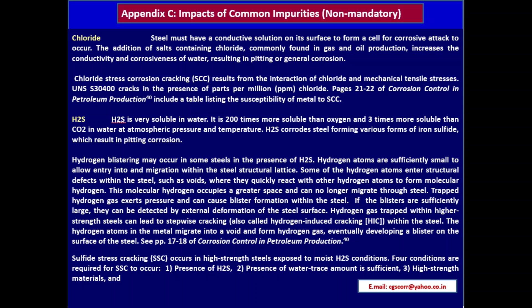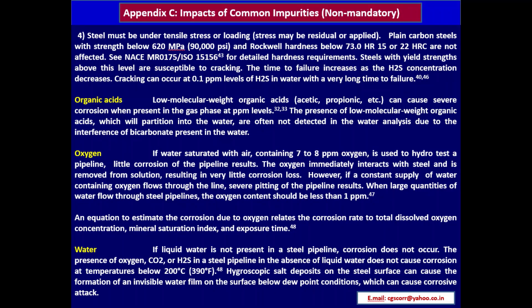Sulfide stress cracking (SSC) occurs in high-strength steels exposed to moist hydrogen sulfide conditions. Four conditions are required: (1) presence of hydrogen sulfide, (2) presence of water (trace amounts are sufficient), (3) high-strength material, and (4) steel under tensile stress or loading (stress may be residual or applied). Plain carbon steels with strength below 620 MPa (90,000 PSI) and Rockwell hardness below 73 HR15N or 22 HRC are not affected. Steels above this level are susceptible to cracking. Time to failure increases as H2S concentration decreases; cracking can occur at 0.1 ppm H2S in water with very long time to failure. See NACE MR0175/ISO 15156 for detailed hardness requirements.